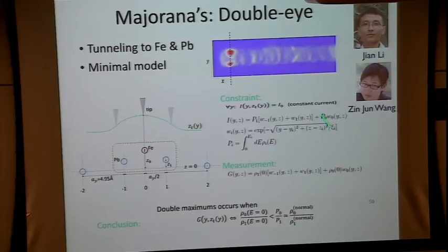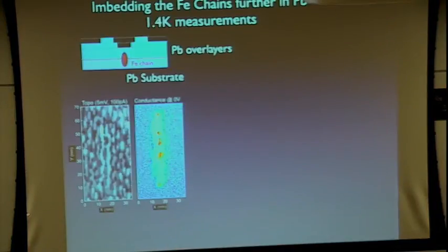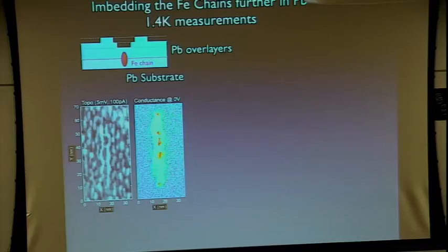But the conclusion of this study was the following: a large part of what we talk about as the Majorana wave function actually lives inside the superconductor. Okay? It's not just living inside this chain at the very end. It's actually a property of the superconductor. So this gave us the idea for another experiment. So why don't we bury the chain? Yes?